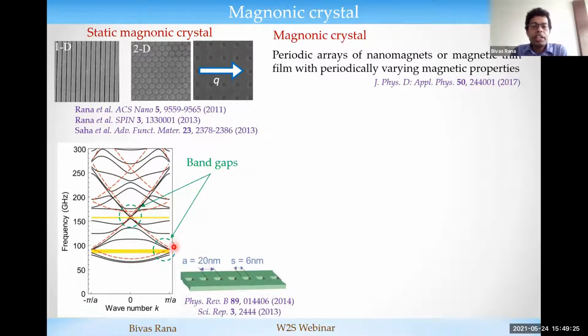So basically you can tune the magnonic bands and create a band gap, and these are very important if you want to apply magnonic crystals for future devices, for example, microwave filters or attenuators and so on. But the problem with this static magnonic crystal is that you cannot change the magnonic bands too much, because the only way to change them is by changing the orientation or the magnitude of the magnetic field.